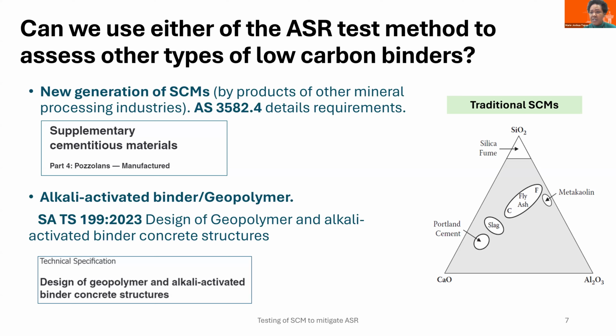So I think the new generation of SCMs will still be within this region. Similar to the traditional SCMs, we have potentially a different type of chemistry, different types of other elements associated in there, but still will be a type of aluminosilicate. So I don't see a reason why we cannot extend the existing standard toward assessing the new generation of SCMs for efficacy and mitigation. The critical thing, though, is understanding the chemistry of the SCM, understanding the test method, and what it does to the system.